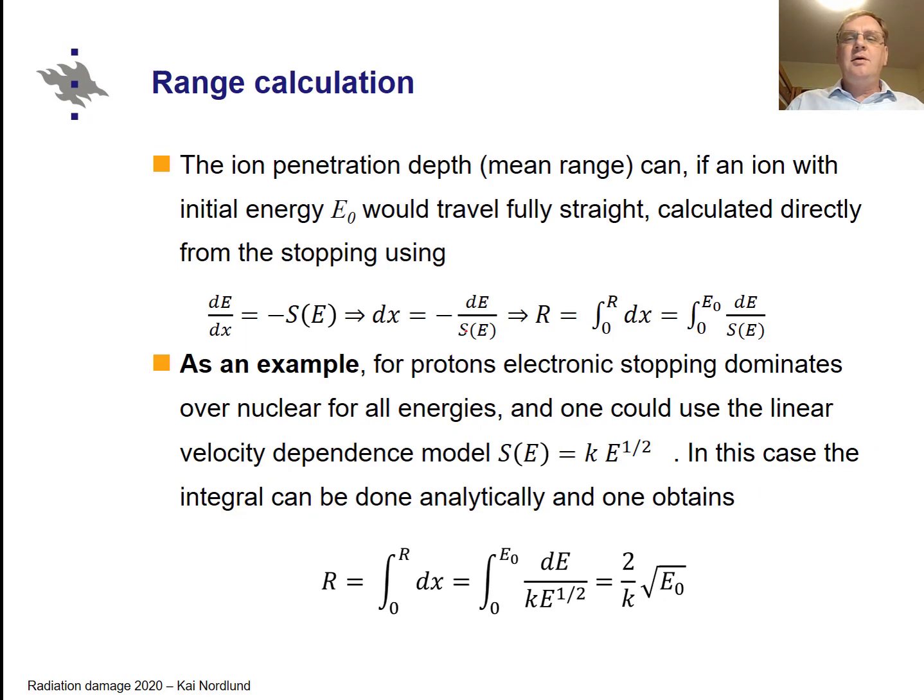And what's more interesting is in most practical cases, we know what the energy is, but we want to know how deep the ions penetrate. And now I emphasize this, that if the ion would travel fully straight, then we could calculate the penetration depth by solving this simple differential equation. So we get dx equals minus dE over stopping power, and then the range, the penetration depth, you would get by integrating this dx, so you would integrate this quantity.